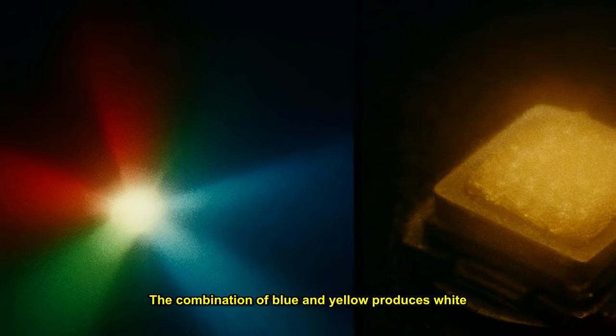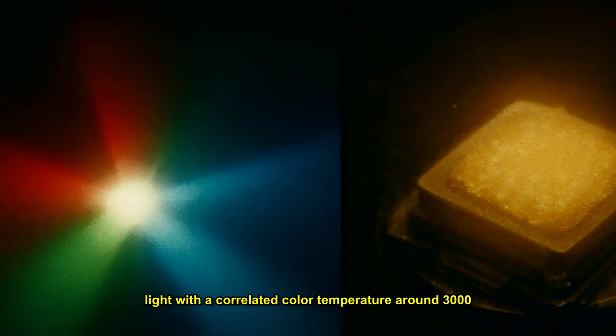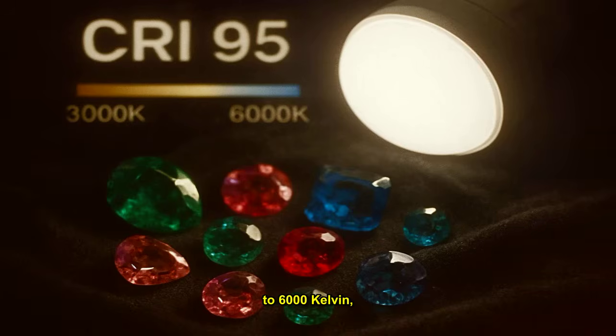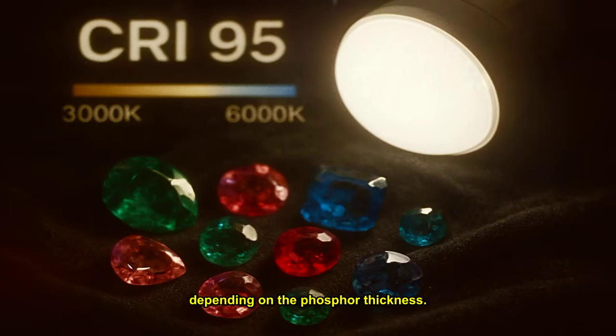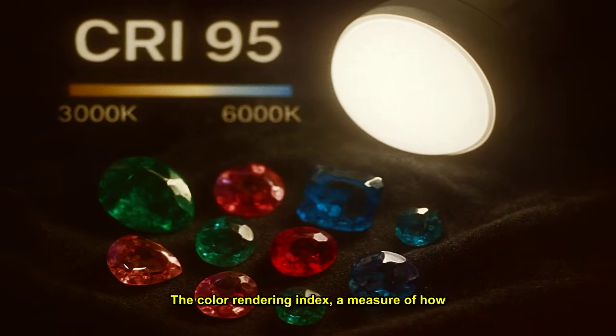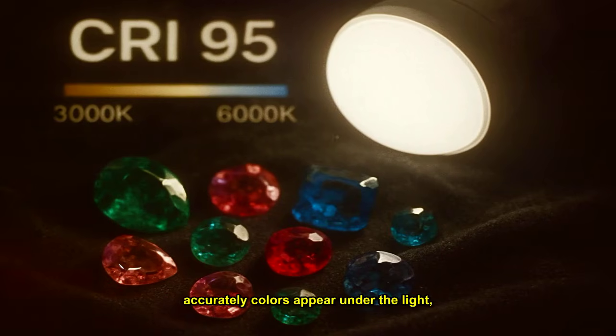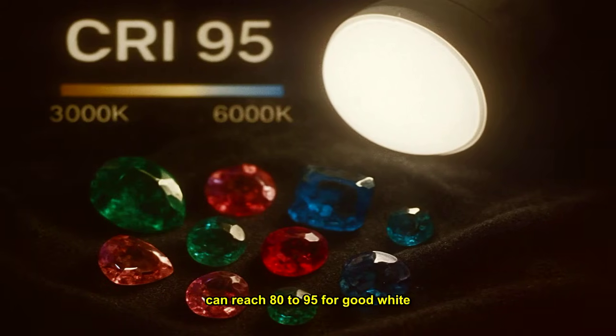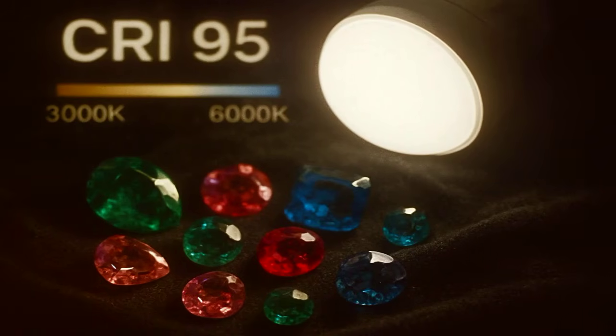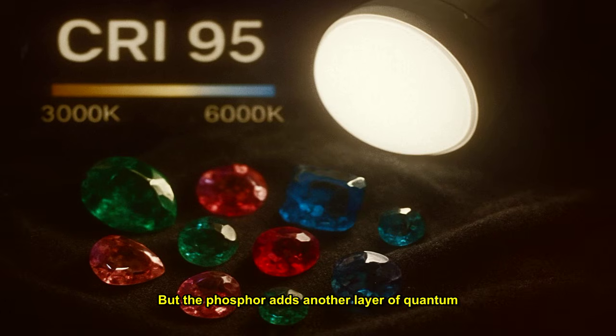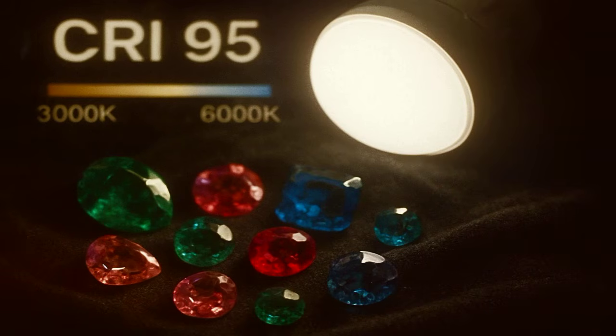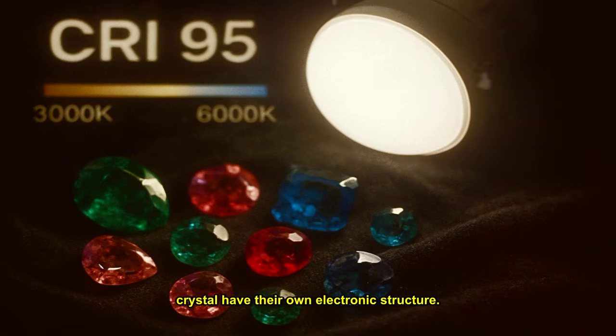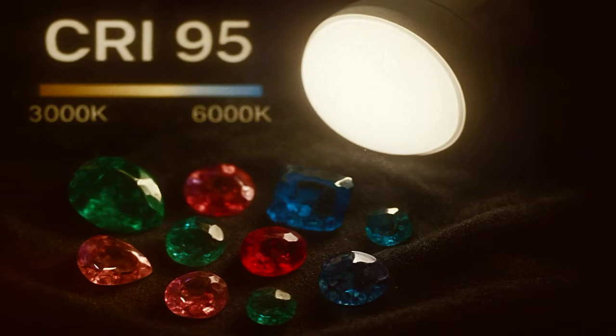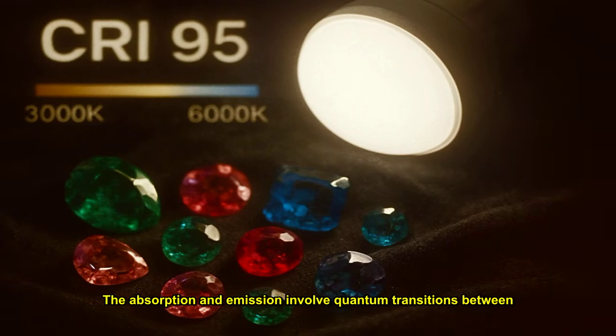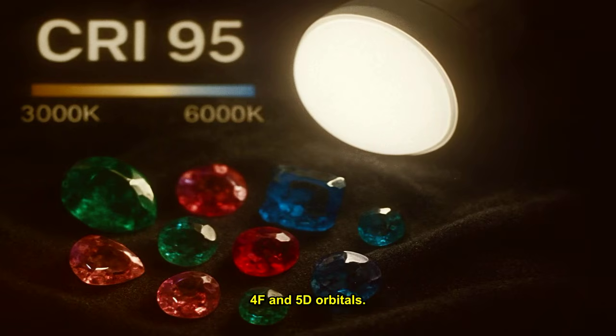The combination of blue and yellow produces white light with a correlated color temperature around 3000 to 6000 Kelvin, depending on the phosphor thickness. The color rendering index, a measure of how accurately colors appear under the light, can reach 80 to 95 for good white LEDs. This is excellent, but the phosphor adds another layer of quantum mechanics. The cerium ions in the YAG crystal have their own electronic structure. The absorption and emission involve quantum transitions between 4f and 5d orbitals.